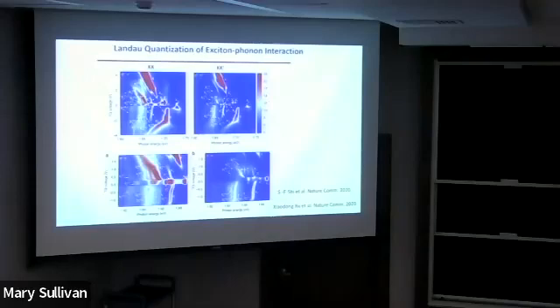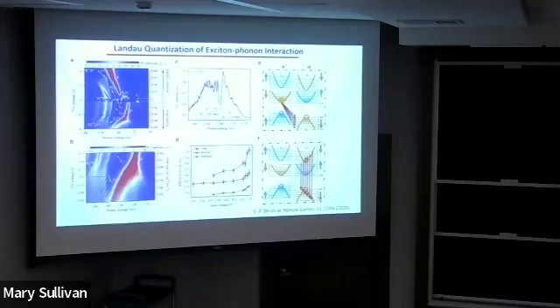So I told you everything from the monolayer, everything up to here. Every peak is not a defect. Every peak is a meaningful quasi-particle. But if you extend the energy even further, we're actually seeing additional peaks, at least 4 here, 4 here. These are phonon replicas of dark trions. Xiaodong also has a very nice paper on this, and we also have a paper on this. But one thing we are interested in is turning on the magnetic field, turning on the Landau quantization, and seeing what's going on. So actually we see something quite cool.